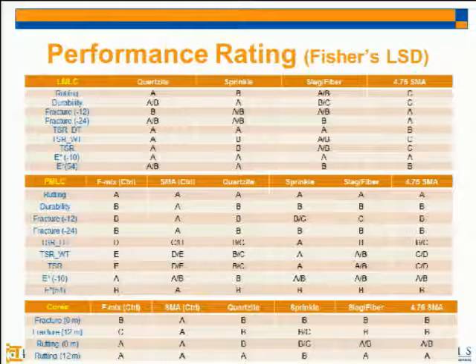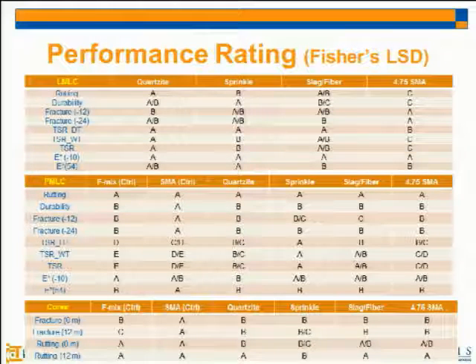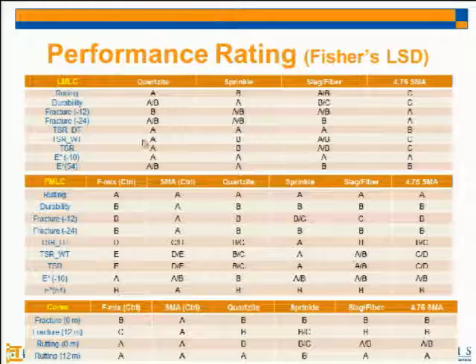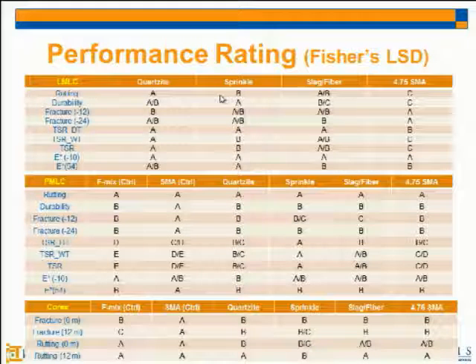Now we have the cost and the performance. To quantify the performance for each test, we use Fisher's LSD statistical method. By using this method, we can rank the mixtures for each performance, A to E or something like that. We put all the raw data in this software and get the rank A to E. If there are A and B, there is a significant difference in performance. So A, the quartzite rutting mixture, significantly performed better than the sprinkle mix. But if we have A-B, that means there's no significant difference between A and B, and their performance was in between A and B.